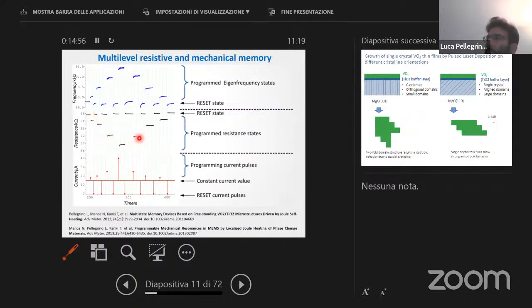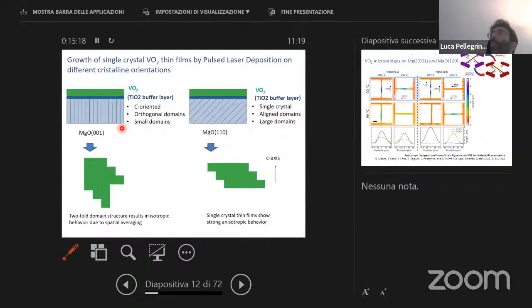So we have a programmed resistive memory. We are not going into details, and you can find details in these two papers on how we can reach this multi-state. Anyway, we are working in the hysteresis window of this phase transition, so we play with the stress and with the electrical resistance of the material.